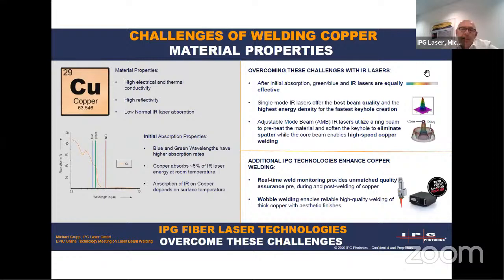We have problems when using infrared lasers, especially at the beginning of the process when we have these solid state materials. What we can do to overcome this is to apply very high power densities. This, for example, can be done when we create a keyhole in a very fast time by using single mode lasers. With single mode lasers, we can create high power densities and create a keyhole very fast and then get stable processes.